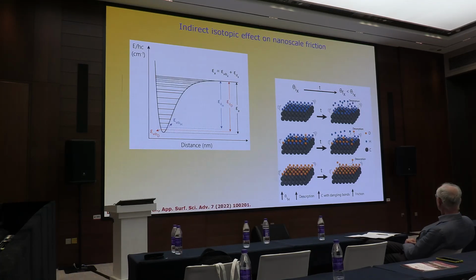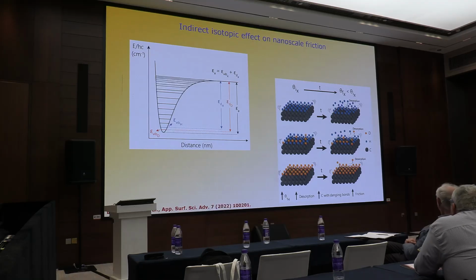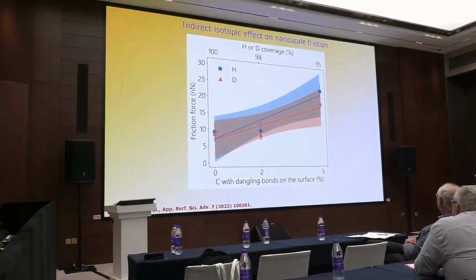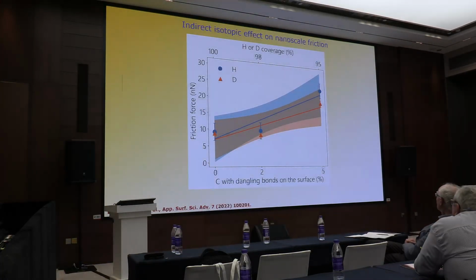I don't have time to explain all the details of all papers, but the conclusion is, when we use this thin film of carbon with deuterium and hydrogen, when we have hydrogen, it desorbs more, and we have more carbon, and with more carbon, we have a higher friction force. This is carbon dangling bond increased friction, because when we use hydrogen, we have more desorption, we have more carbon exposed, or dangling bonds with carbon, and this increases friction.